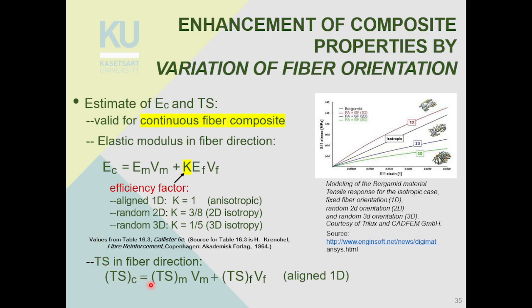Okay, tensile strength in fiber direction. The tensile strength in fiber direction is the tensile strength of the matrix multiplied by the volume fraction of the matrix, plus the tensile strength of the fiber times the volume fraction of the fibers if it is aligned 1D, right? Because if it is aligned 1D, the K factor, the efficiency factor, is 1, right? When it is anisotropic, the K value is 1. But if it's random 2D, the K value is like 3/8. If it's random 3D, then it's 1/5, etc. Right? So you have to choose the efficiency factor accordingly, depending on the alignment.